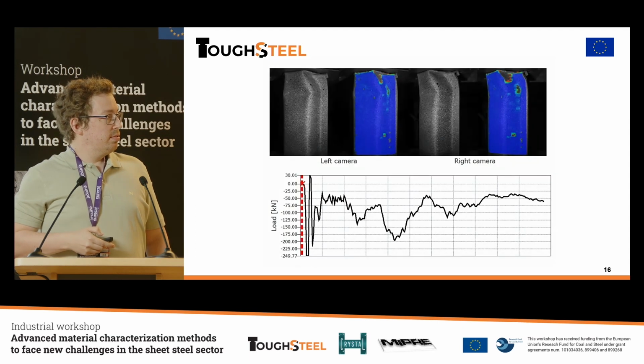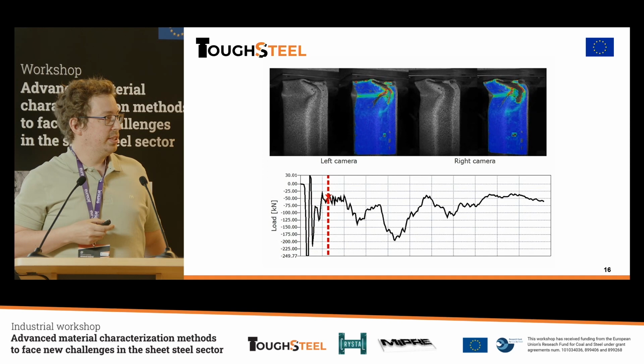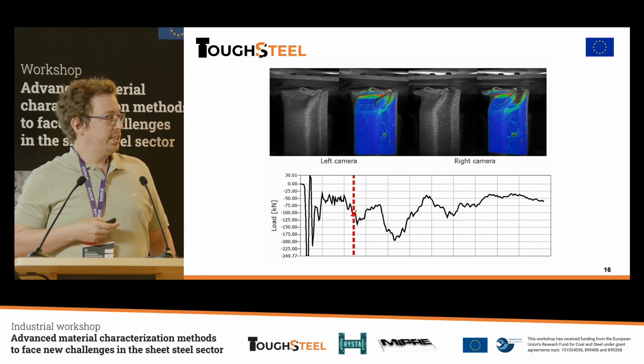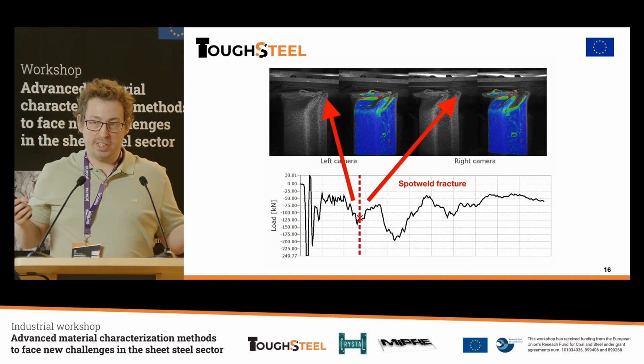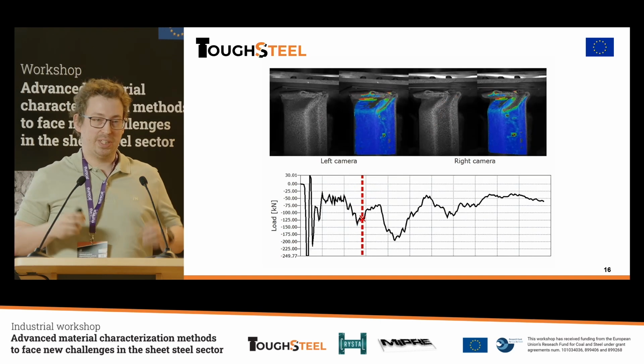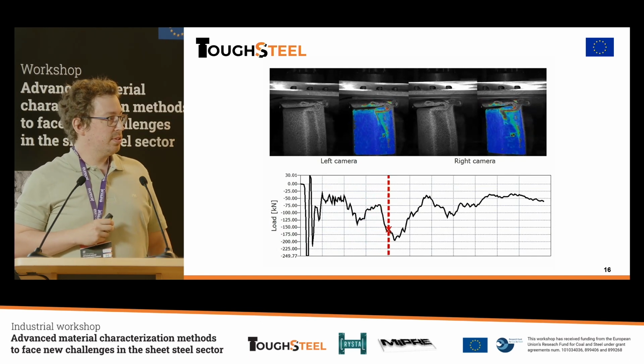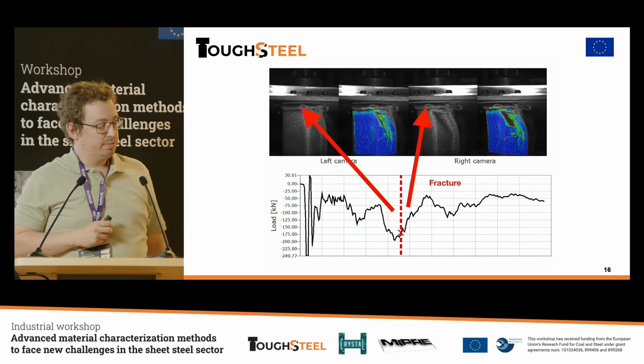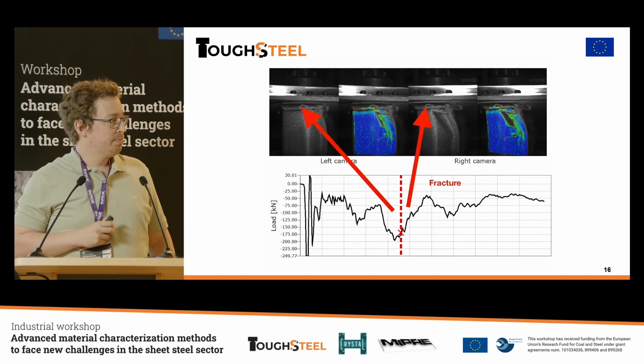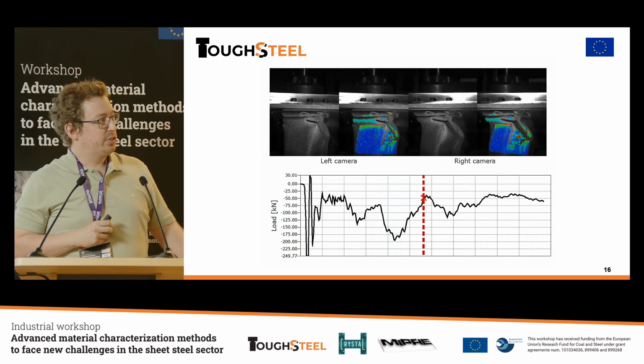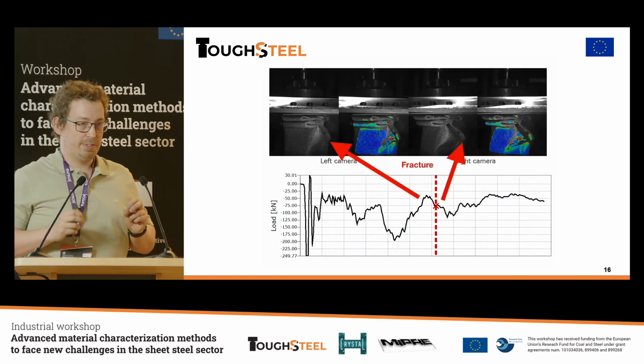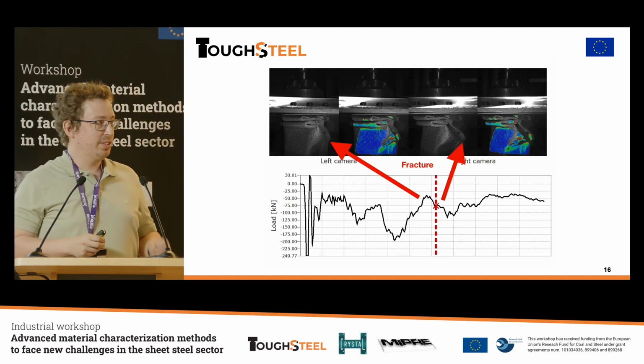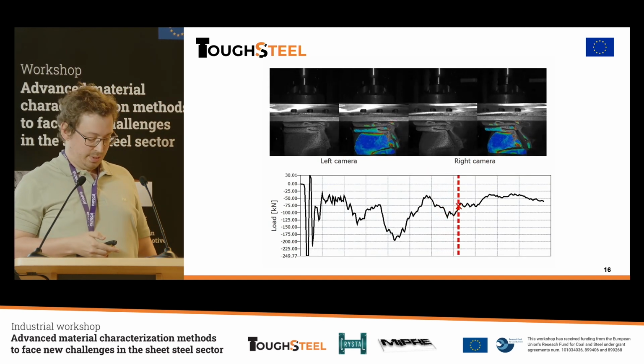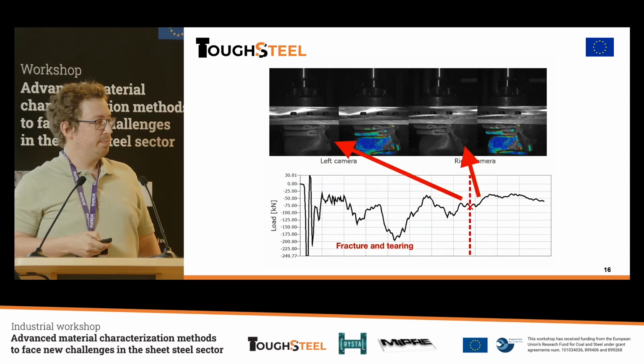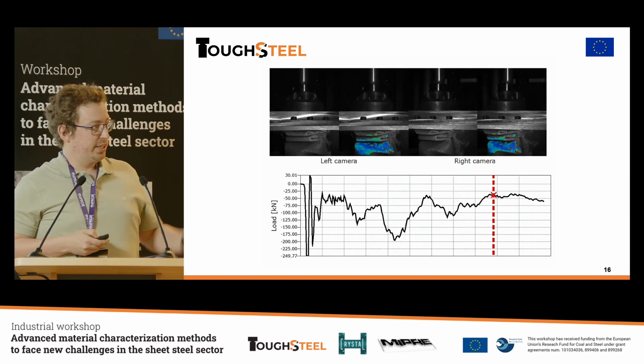So doing this, you can of course capture video and identify when cracks happen, or when spot weld fractures. We're generally not interested in spot weld fractures because we can't really trust the material in those spots. And of course we have the intrusion depths and the loading histories here. And also we have some strain field here because we want to validate this with a finite element model. I won't show that simulation here, but we wanted to do that as well. So we tried to get the facets field of that as well, so we can identify the cracks when they initiate and how they propagate in the end.